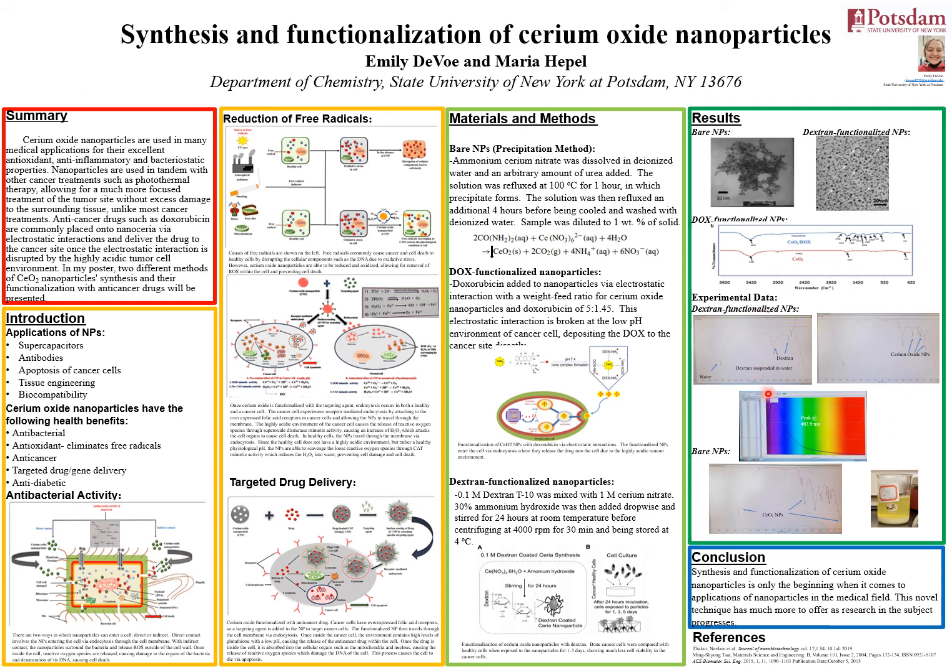Onto my data, this is for the dextran functionalized nanoparticles. There's dextran suspended in water, you've got the water peaks and the dextran's peaks, and then over here I've got the cerium oxide nanoparticle IR scan showing that there are additional cerium oxide nanoparticles with the dextran on there. An absorbance scan showed that there is maximum absorbance at a peak of around 403 nanometers, and this value is proportional to the amount or concentration of nanoparticles present.